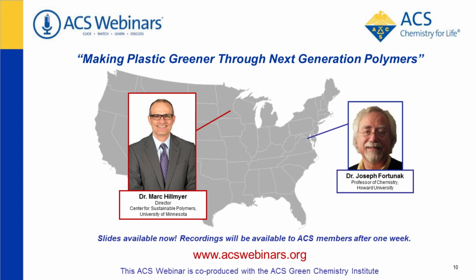Now, that puts a limitation on an upper temperature limit. So if your glass transition temperature starts to creep up towards your degradation temperature, that can provide challenges from actually processing the material. Something we definitely think about, something we're concerned with in the case of these block polymers that I told you about with polylactide and polybetamethyl valerolactone, they will ultimately degrade at high enough temperature. And so there are limitations on the extrusion process that are going to be important.